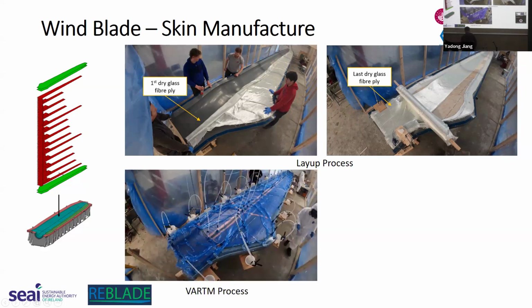So then the VARTM process, or the infusion process: the vacuum bag is in place, and all the resin pots are ready to go as well. So we'll fill them up with resin, and then we pull a vacuum. So we draw all the air out of the vacuum bag, create that pressure differential, and then the resin will be sucked into the parts. I'll show you a quick time lapse, and you should be able to follow the resin. The resin will start penetrating from the root, and then you'll see it slowly move up the blade. Hopefully you can see it all right.